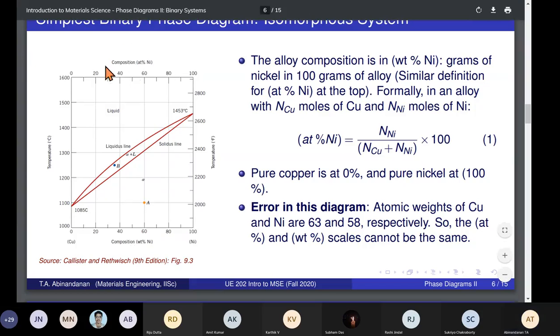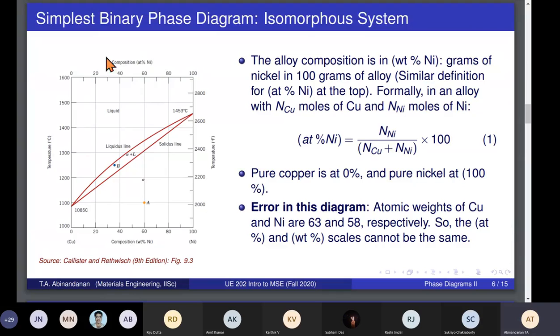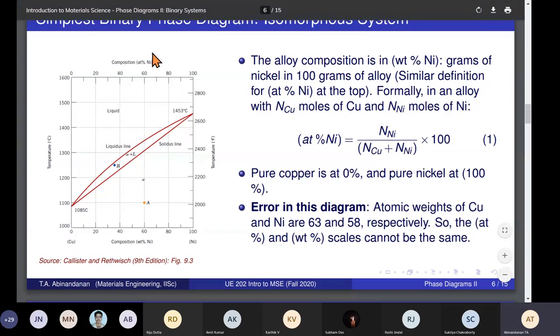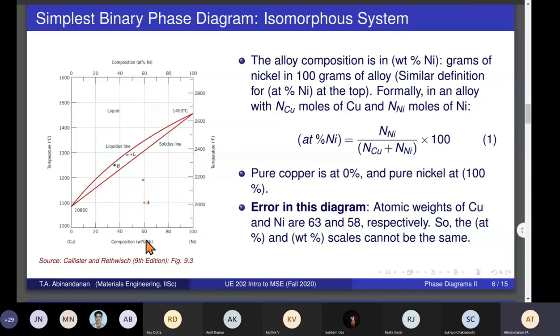But in materials and in physical sciences largely, we deal with the atomic fraction, and that is also given here for convenience. But one can go from the atomic fraction to weight fraction quite readily using the atomic weights. And this is where I noted this. There is an error in this diagram. Since the atomic weights are different, they differ by about 10% or so. These two scales cannot be the same. And there is an error here. Maybe we should point this out to Callister.